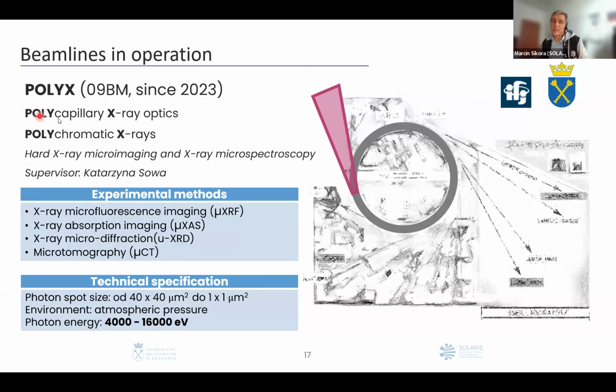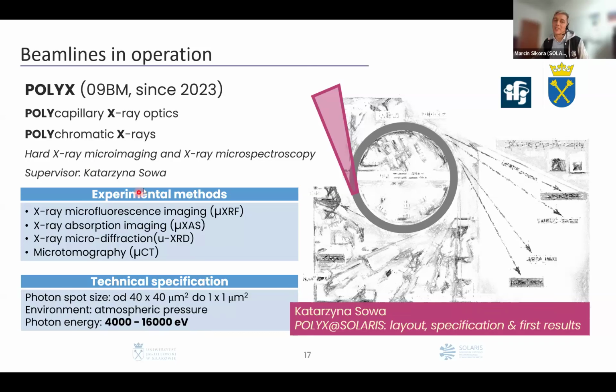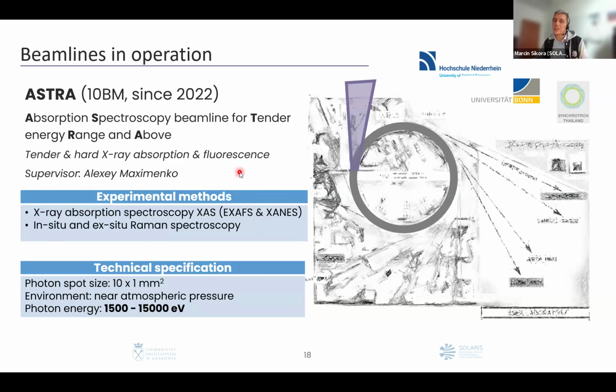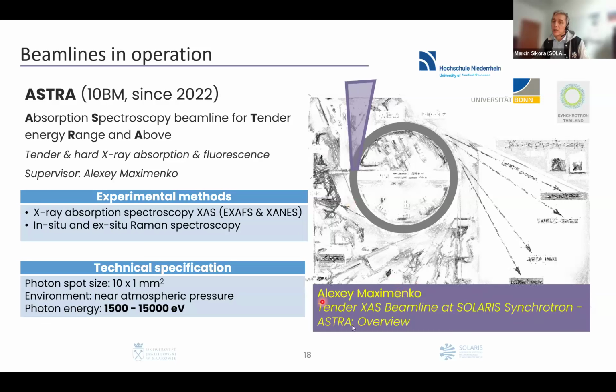Yet another beamline is POLYX, polycapillary X-ray optics and polychromatic X-rays. It's a beamline that operates in the hard X-ray energy range, but this one will be very nicely presented, and you will see more results and highlights by Katarzyna Sowa directly after my talk. And another beamline in operation is Astra, which is for X-ray absorption in the tender energy range and hard X-ray energy range. These two beamlines, the recent ones, have photons from bending magnet radiation. They were recently opened in 2022, 2023. And for Astra, there is application of many different X-ray spectroscopy measurements. A Raman probe was also recently installed, so you can characterize your material and perform some operando experiments. Alexei Maximenko will present the opportunities and highlights of that beamline.